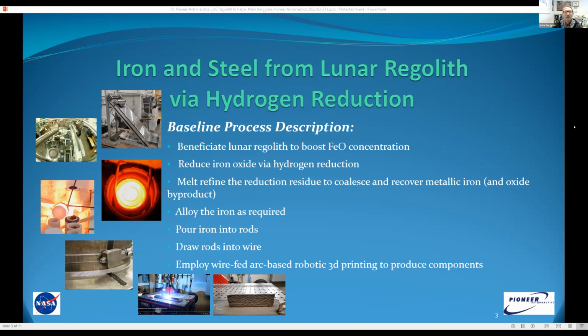We would then go to iron oxide reduction on the concentrated regolith using hydrogen reduction in an automated apparatus with some durability and hopefully long-lived hardware. The residue from reduction would advance to a melt refining step where we bring the material up to a temperature that allows the metallic iron to coalesce and separate for recovery, then leaving us with an oxide byproduct.